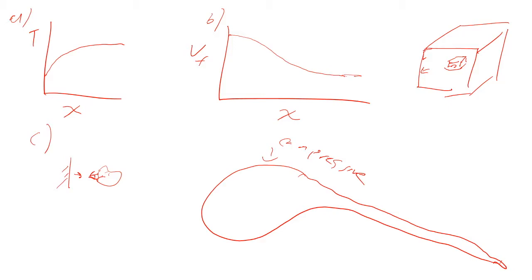Yeah, right. I still have some surface compression out here, right? There's still a gradient, right? But it's not nearly as much as up here, right? So now I get a crack, right? I get cracks that propagate in from this little end. What's going to happen? I've got an imbalance of forces here.